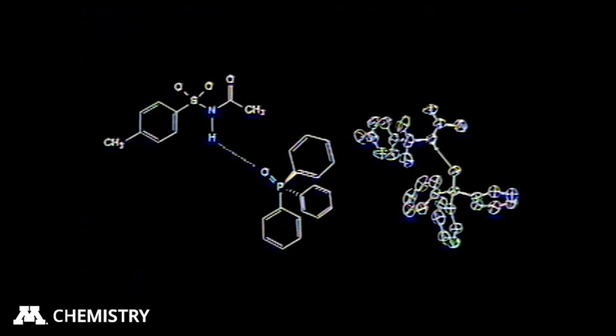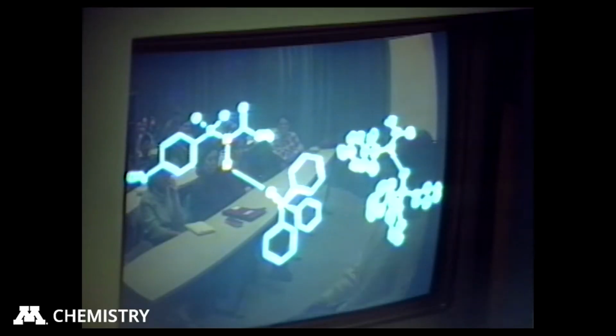I'm showing on the right an ORTEP of the crystal structure, and on the left just a schematic. So here's a way, by introducing a guest molecule into a system, we can put our original molecule into a new environment. And by changing the groups on this guest, we can change the environment almost with infinite versatility. And what I'm showing you here is there is an added bonus to using triphenylphosphine oxide. This is one of those things we weren't looking for, and we almost missed this effect, in fact.